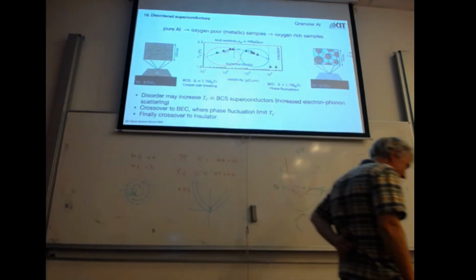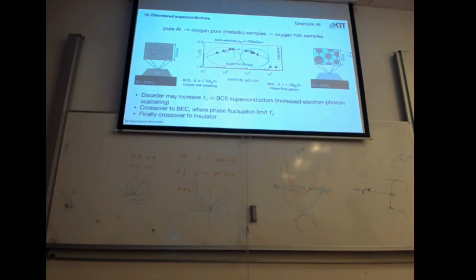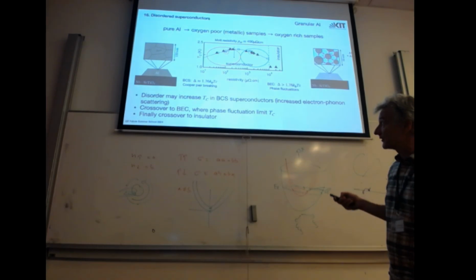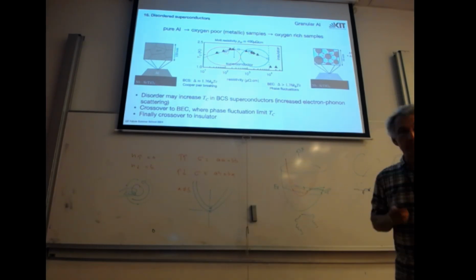Since disorder plays a role in this school, I also want to look at disordered superconductors. The only samples I looked at personally are aluminum, which is called granular aluminum. So you go from pure aluminum to oxidized samples, and you basically grow the sample by depositing aluminum with an oxygen back pressure in your chamber. So you will get a mixture of aluminum and aluminum oxide. If there's no oxygen in your chamber, you basically get a pure aluminum film.